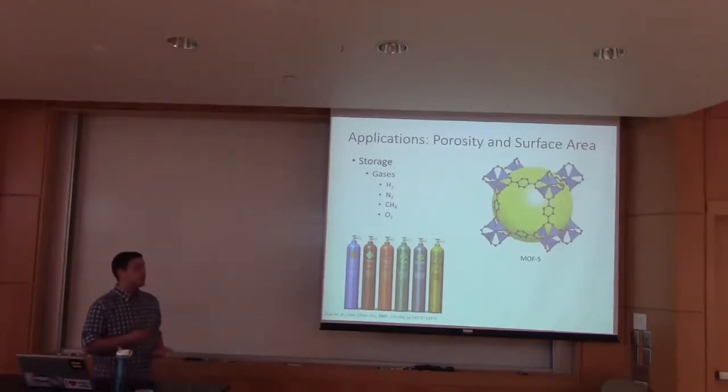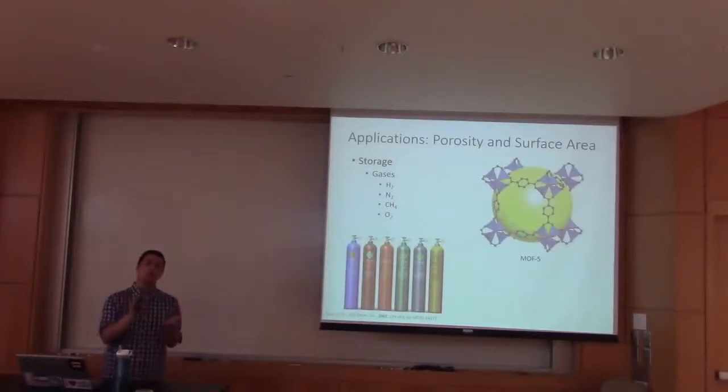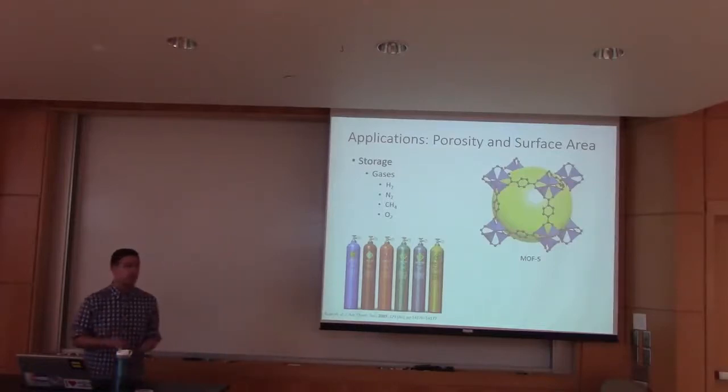So what's really groundbreaking about this is if you want to store a gas, obviously normally we just put the gas in a canister at high pressure. Well, with a MOF, you can put the MOF into the canister, and then you can put the gas in there, and the gas molecules will actually adhere to the MOF structure. And because they are no longer acting as gas molecules, they won't contribute to the partial pressure anymore, and so you can store more of that gas in the storage container at a lower pressure, which has applications in a lot of fields like natural gas and plenty of other fields.